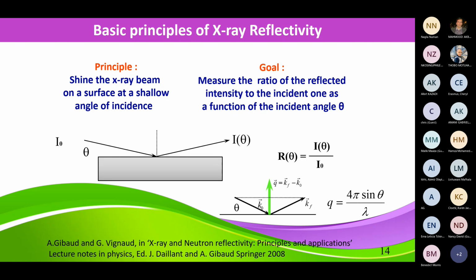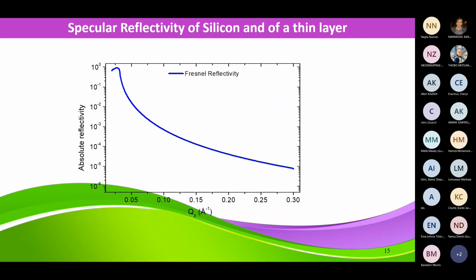Just to show you what it is, you can describe it either as a function of theta or as a function of the Q wave vector transfer, which is 4 pi sine theta over lambda. If you do it on just silicon, you see the reflectivity is close to 1 at very shallow angle here. It's 1 here. And then it's decaying very quickly, several orders of magnitude, as a function of a very small variation of the angle or of the Q wave vector transfer. You can see that it's decaying as 1 over Q to the 4th. That's a very, very sharp decay.